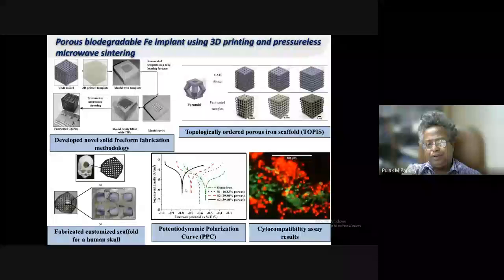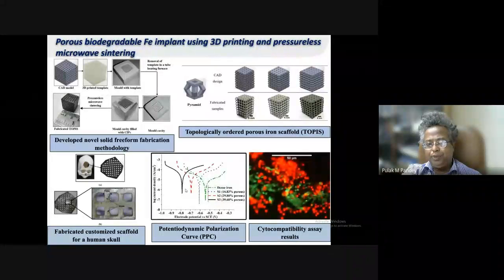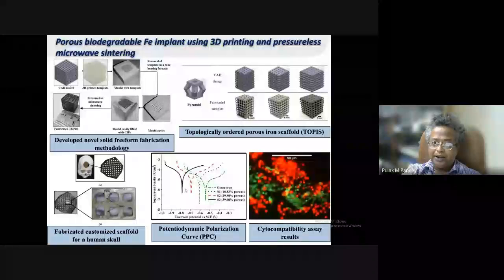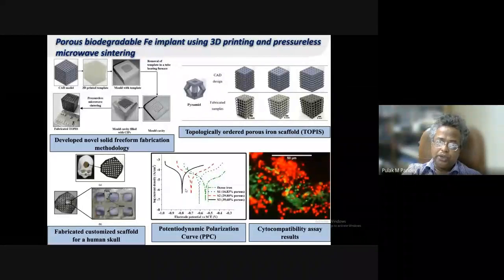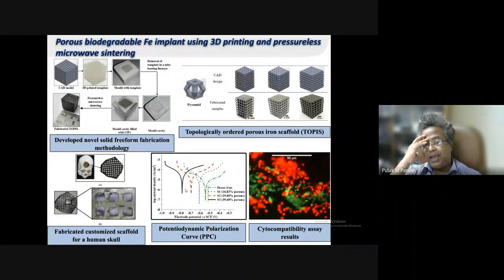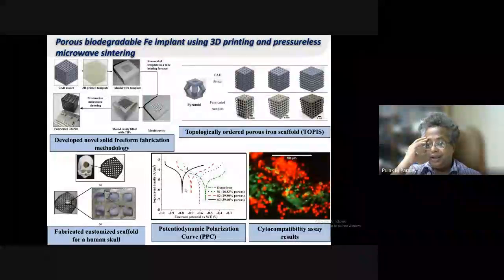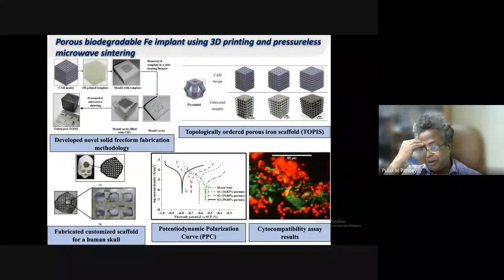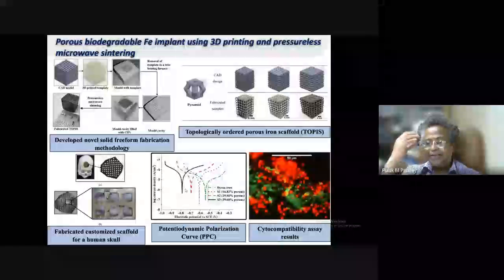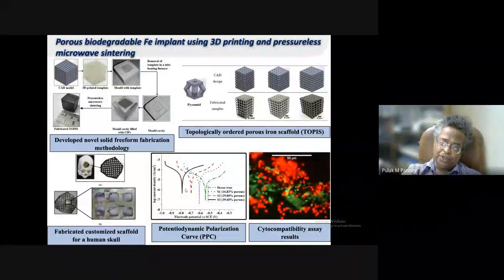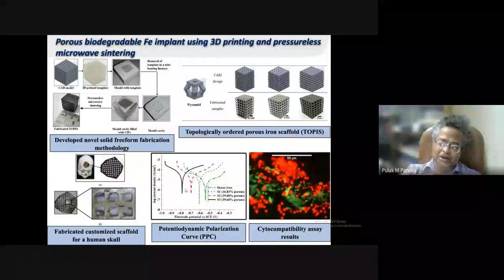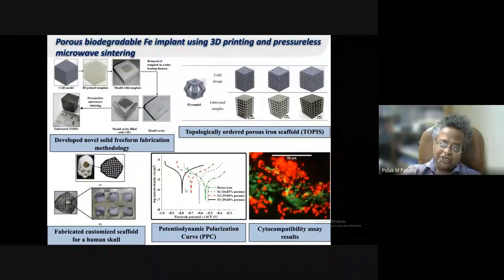We have developed biodegradable pure iron implant, because now again the trend is biodegradation. So if you are using pure iron as an implant material, it has stress shielding problem, and at the same time its degradation rate is very low. So we have tried to improve its degradation rate and reduce the problem of stress shielding. So we have developed our own system.